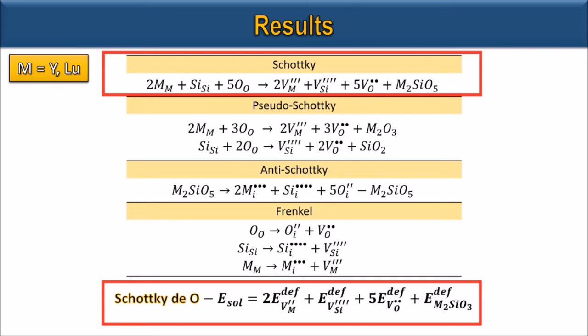The solution energies were normalized by the number of point defects present in the final defect configurations according to the related reactions in this table. As an example, the solution energy obtained for the Schottky defect was divided by 8, since this defect presents 8 individual point defects: 2 yttrium or lutetium vacancies, 1 silicon vacancy, and 5 oxygen vacancies.